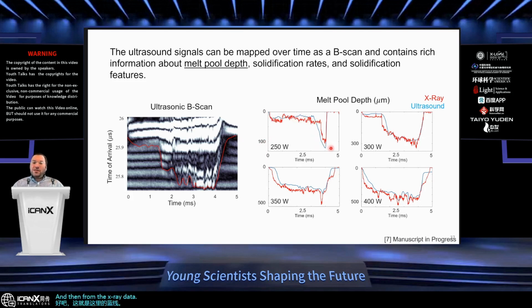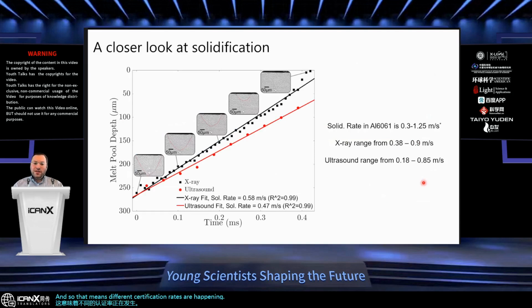And then from the X-ray data, we can plot the depths of the melt pools, and we can put those over top of each other. And you can see the very, very nice correlation between the X-ray depth and the depth recovered from the ultrasound. Right. And then if we focus on where solidification happens at this point, you can see different slopes. And so that means different solidification rates are happening.